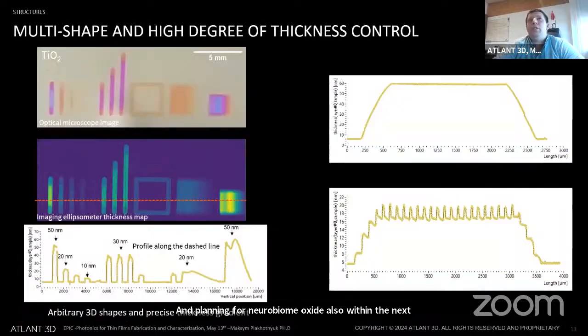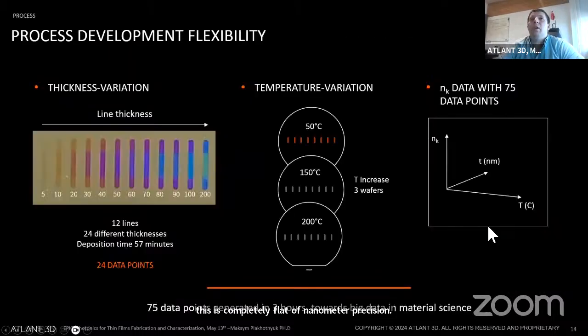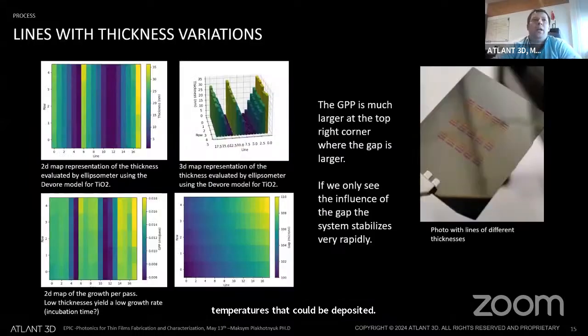What we do with this technology, we have flexibility in thickness control, geometry control, gradient thickness control, roughness control, so we can easily modulate roughness. As you could see, this is a comparison of two surfaces which we rastered. So this one is completely flat with nanometer precision. This one is with structures. We easily have flexibility over process development. So variation in the thickness, as you could see, from 5 nanometers to like 200, and on the same wafer variation in the different temperatures that could be deposited. And this is one of the examples. So these structures were deposited on the same element.